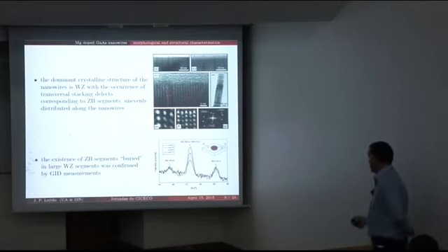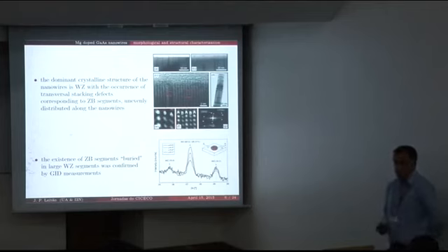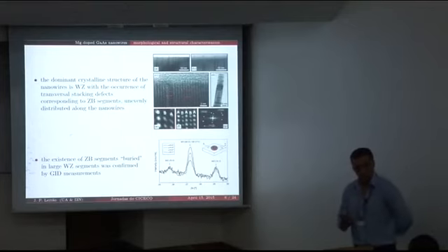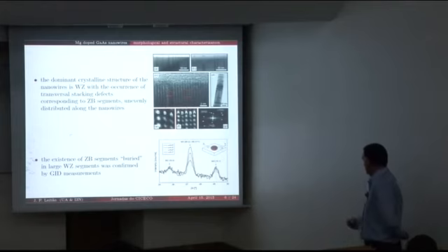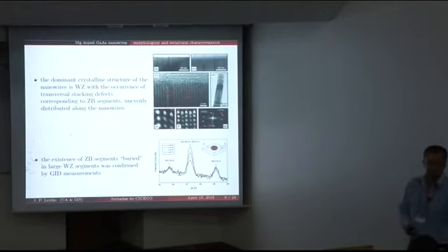So we try to reduce the incidence angle here, as shown, in order to avoid precisely the influence of that epitaxial layer. We observe that as we reduce the incidence angle, the relative intensity of this peak diminishes clearly, and is more or less close to the relative intensity of the other two peaks.